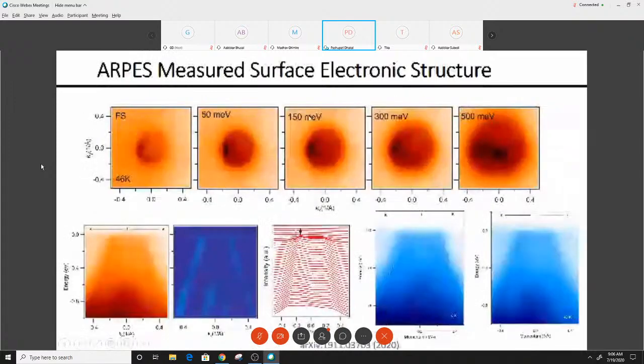To confirm the disappearance of the inner band in the paramagnetic phase, we also performed measurements at 46 Kelvin. These are all measurements at 46 Kelvin, and similar to the data at 22 Kelvin, we see that there is no extra feature apart from the hole band in the vicinity of the Fermi level.